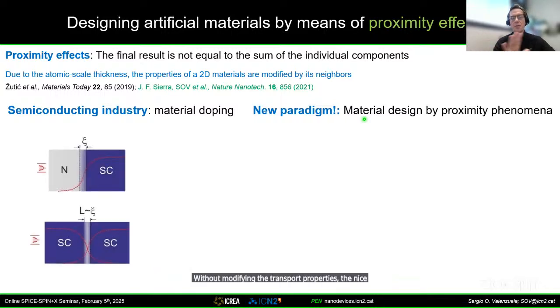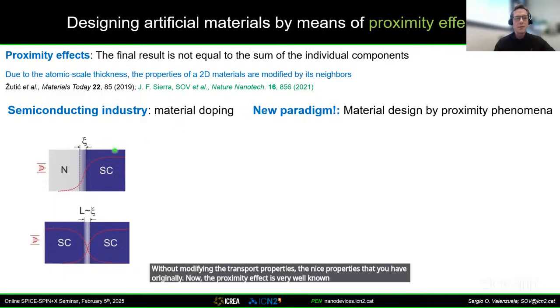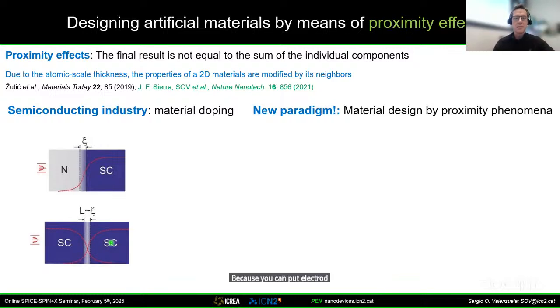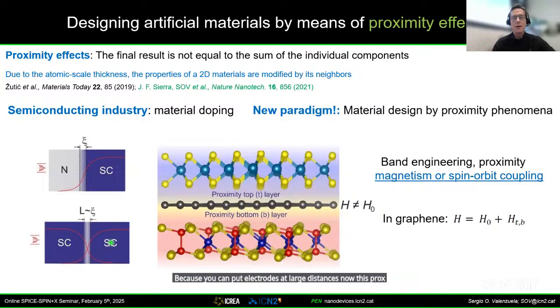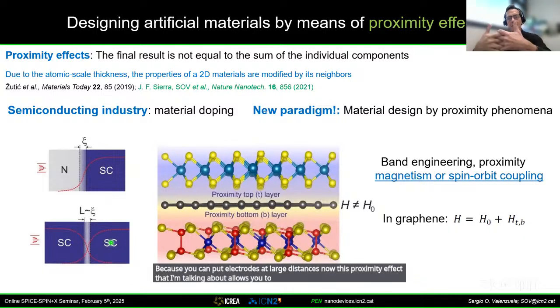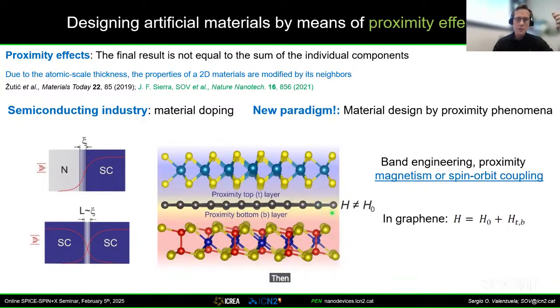Now, the proximity effect is very well known in superconductivity, and the reason is because it occurs over distances of the coherence length, which can be hundreds of nanometers. You can have a superconductor, a normal metal, and a superconductor, everything in a lateral device, because you can put electrodes at large distances. Now, the proximity effect that I'm talking about allows you to investigate proximity phenomena very clearly for magnetism or spin-orbit coupling that occurs at much shorter distances, which are typically atomic distances. But because this material is atomically thin, you can really modify the band structure of a whole volume or a whole surface of your system.